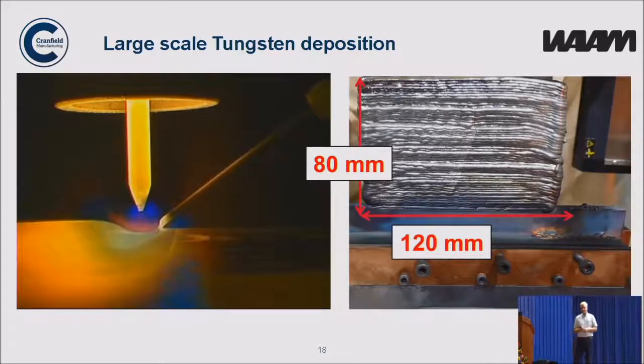As an example, the video on the left is showing tungsten deposition. This is using TIG deposition actually, and we were told by the laser powder people that we'd never do tungsten deposition with an arc because we couldn't get it hot enough. As you can see, we have a very nice stable process with continuous metal transfer, and we were able to produce very large structures completely free from pores.